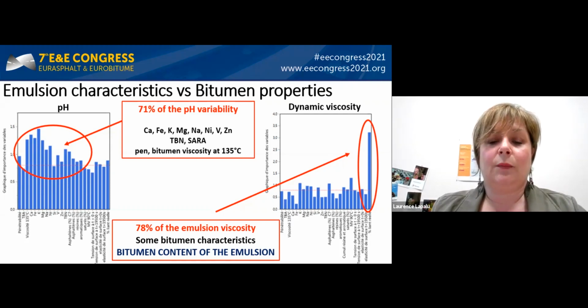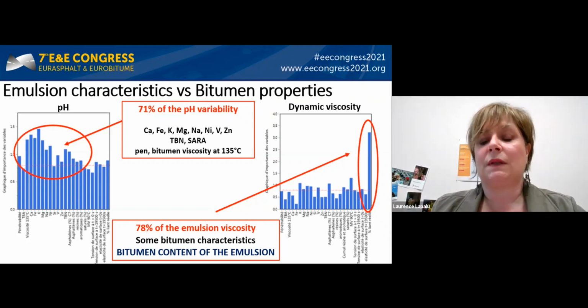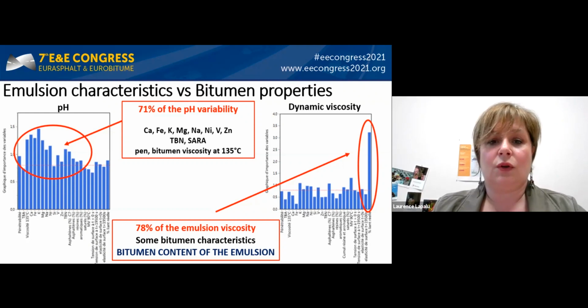The other 29% of the pH variability are linked to other factors, such as the experimental conditions to produce the emulsion. If you look now at the graph on the right, representing the dynamic viscosity, you can see that 78% of the emulsion viscosity is linked to the bitumen variables. And in this case, you can see that the bitumen content of the emulsion is by far the most important parameter impacting the dynamic viscosity of the emulsion.